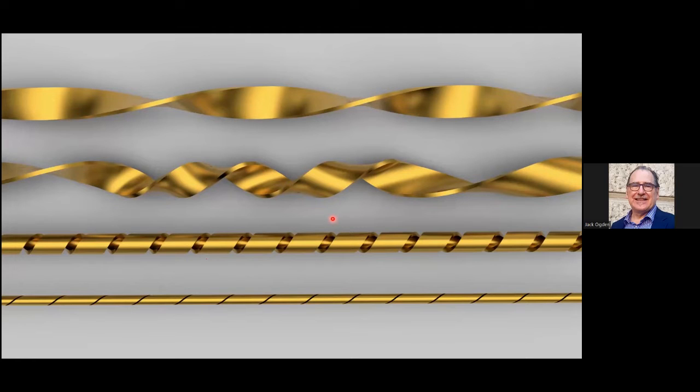Take a strip of gold, twist it just between your fingers, twist it tighter and tighter and tighter. And it's a sort of physical thing that if you tighten it, eventually it goes into a nice little regular coil. Tighten as much as you can, and then roll it between two flat surfaces. When you've done that, you have a perfect wire. And it is extremely regular and very circular. And they can do very small diameters.